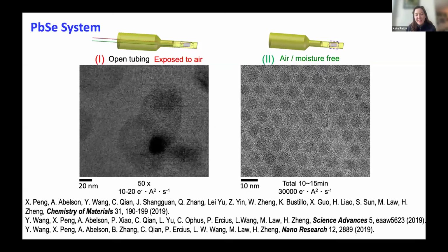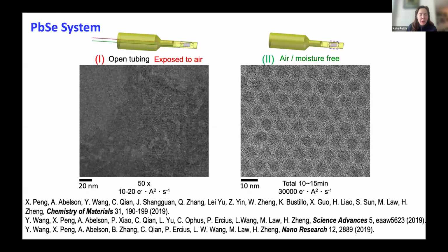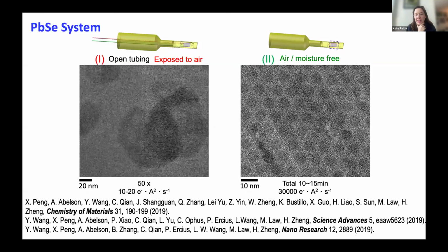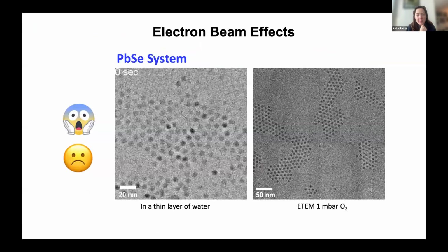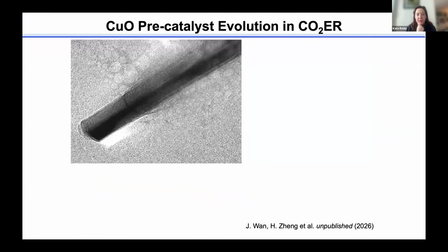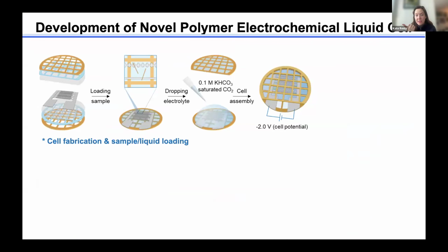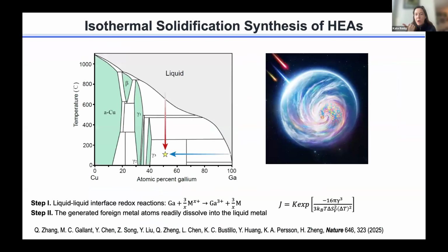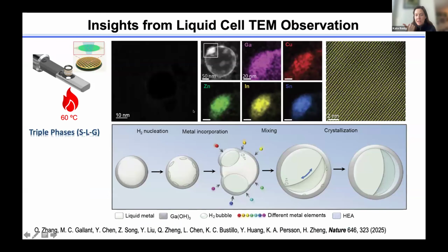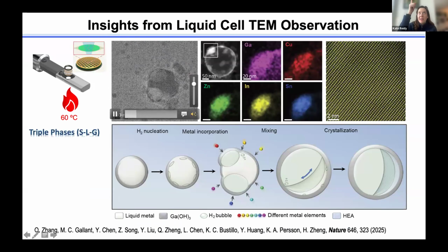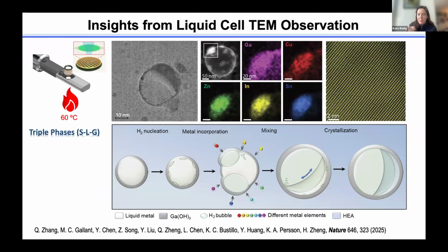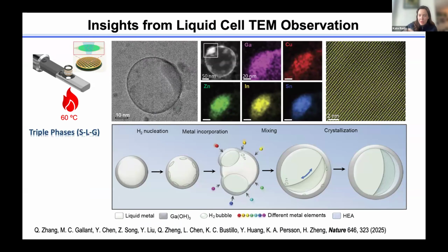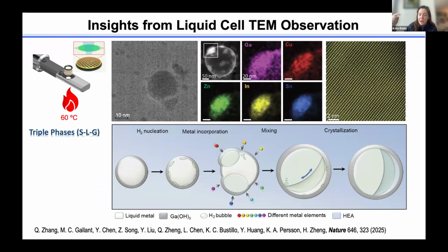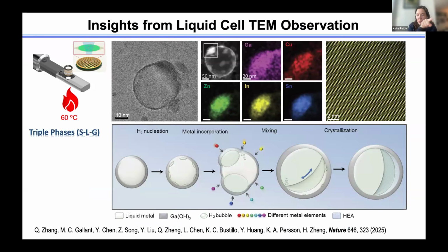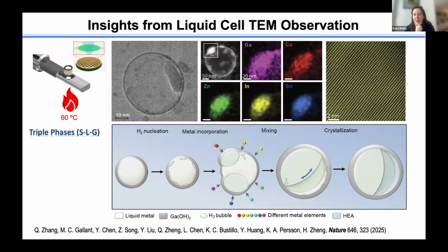Thank you so much, Jaime. I had a similar question to Bob, but on your isothermal synthesis of the high entropy alloys. I really enjoyed that aspect. Number one, do you think radiolysis is a large part of why you can synthesize these out-of-equilibrium structures? And number two, when you're going down in a phase diagram in temperature, you know what your composition is, for that quenching of the high entropy alloys. But when you're doing this new isothermal synthesis route, how do you determine where in the phase diagram you're going to end? Where in temperature, but also where in composition?